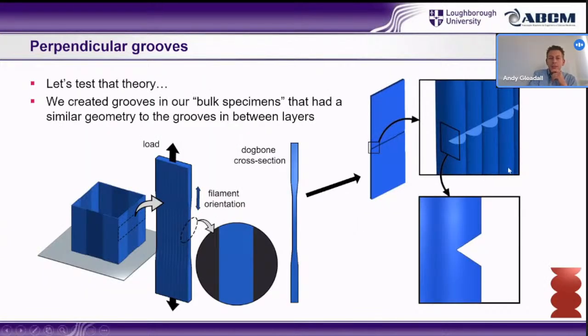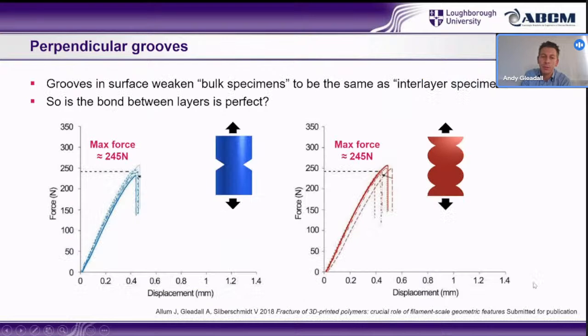And we tested this theory by taking one of the specimens that was solid, that was printed and tested along the direction of printing, and we manually scored it with a little blade to create a groove that was the same size as the grooves in between the layers. And once we did that, the force we got was exactly the same in this case. I'm not saying it's exactly the same every time, but it's within experimental error.